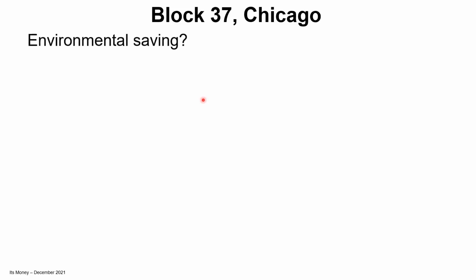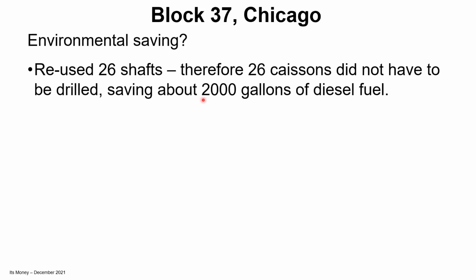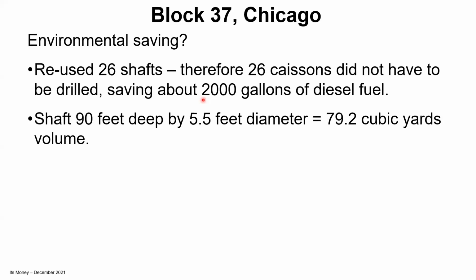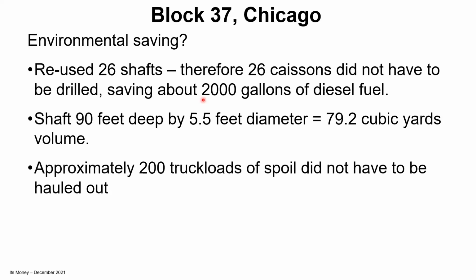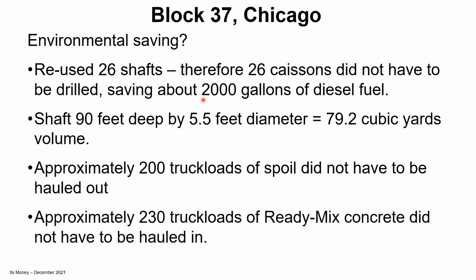But the real kicker was the environmental saving. Reusing the 26 shafts, the contractor's estimate saved about 2,000 gallons of diesel fuel. The shafts were 5.5 feet in diameter and 90 feet deep, so almost 80 yards per shaft. So over 200 truckloads of spoil didn't have to be hauled out, that's assuming you're using 40-ton trucks. And 230 truckloads of ready mix didn't have to be hauled in. So again, the savings were real and the environmental benefits were significant.